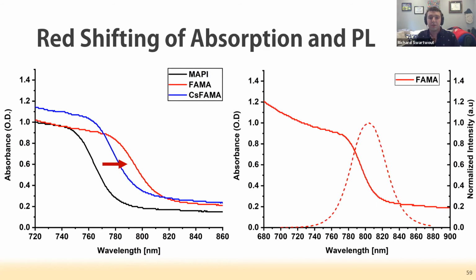This is also true with the PL spectrum, which shows a peak height around 805 nanometers with no off peaks. So you'd expect that if it's not phase pure, you'd get something around 780, which is the emission peak expected from a methylammonium lead iodide film.